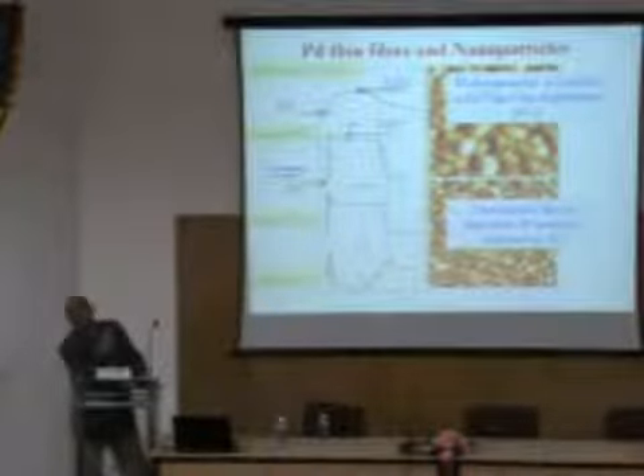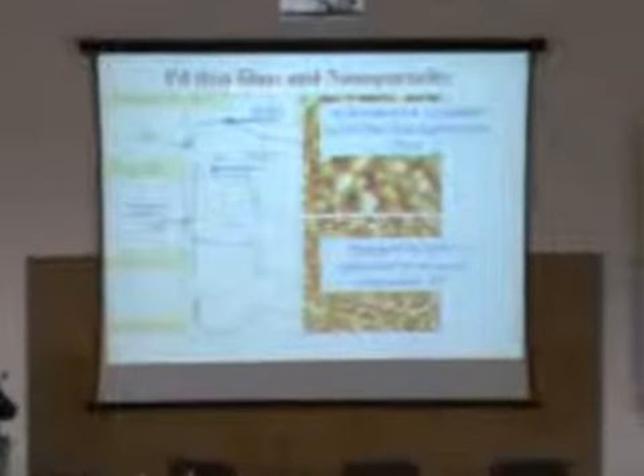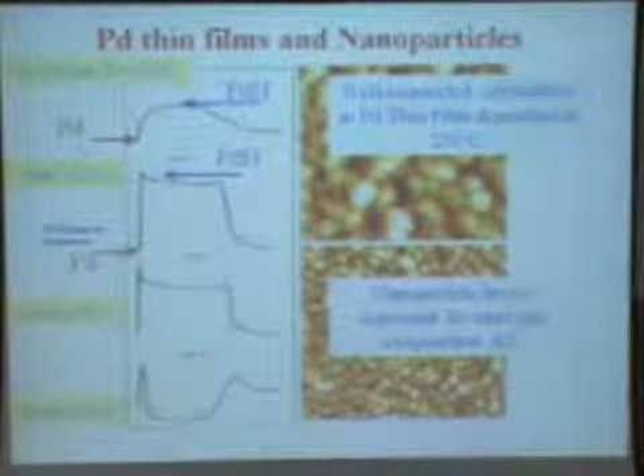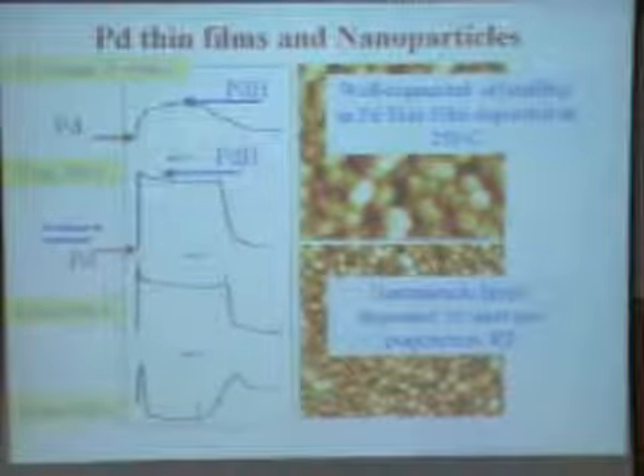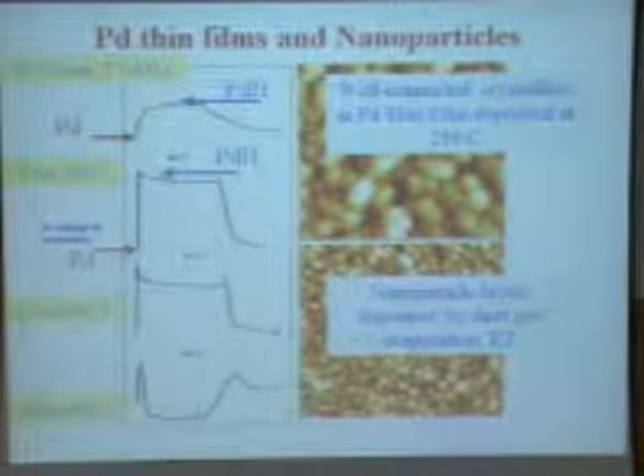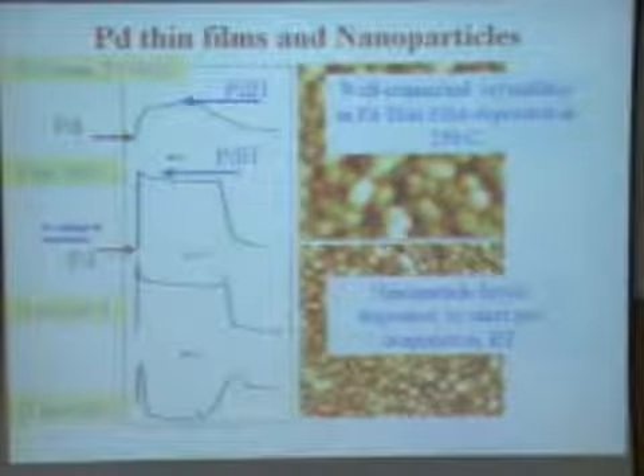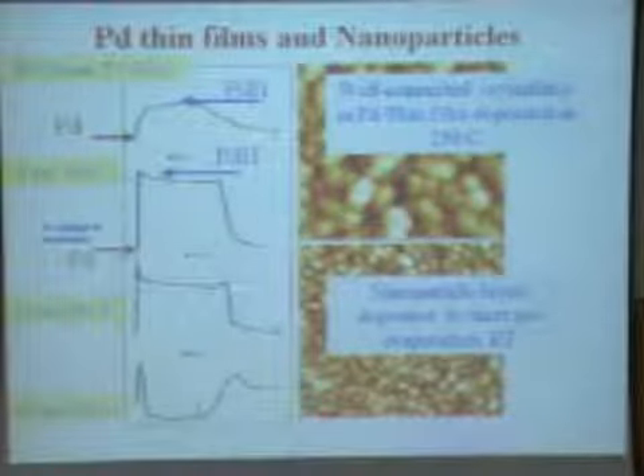You can see that the moment we change the palladium thin film, this is how a palladium thin film interacts with hydrogen gas. What I'm showing is the electrical resistance of the palladium film. You have a palladium film, you put two electrodes, measure the resistance, and expose it to hydrogen. When there was no hydrogen, this is the resistance corresponding to palladium. As the material is exposed to hydrogen, the resistance starts increasing slowly. It slowly increases and then saturates. And when you remove it from hydrogen, it comes back.